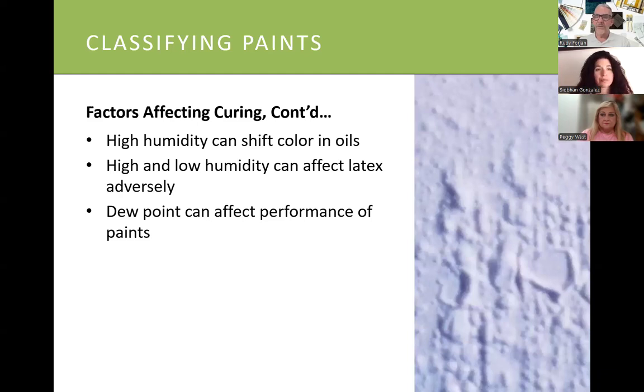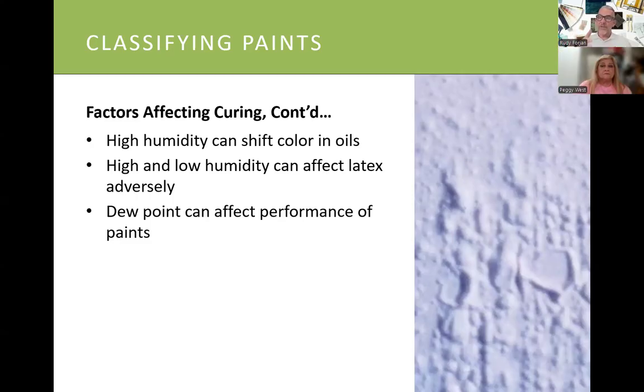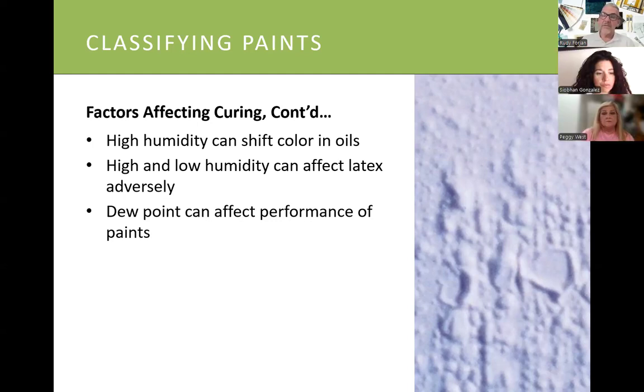High humidity can shift the colors in oils. I'm not going to talk about that because we don't use a lot of oil-based paints anymore. But high humidity can affect latex, and we talked a little bit about where that happens. But with dew point, you don't want to paint on the outside and have some dew land on that coating, especially if you don't give it the time to cure properly. This usually happens when you're going with, say, a dark color outside, generally with a latex paint, where if you get a certain amount of water, or that dew, getting on the substrate itself, you can cause some discoloration of the paint. And a lot of times we get something called